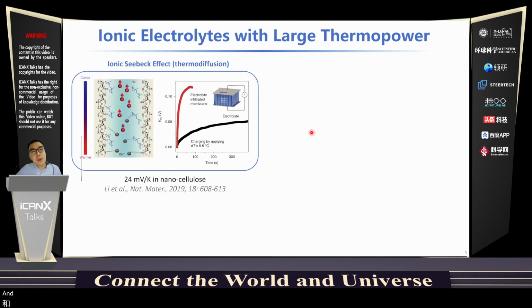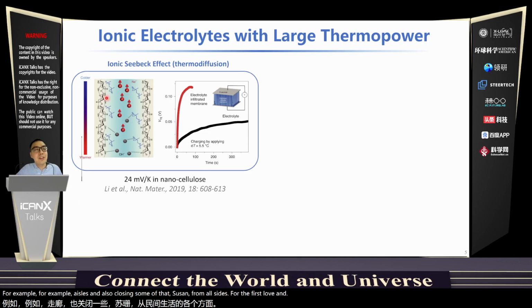In recent years, people found out that ionic electrolytes could be a promising energy carrier for harvesting low-grade heat. For example, ions can also go through thermal diffusion from the hot side to the cold side. And researchers have found that if you can confine these ions in very thin nano channels, you can actually achieve a very high thermopower.